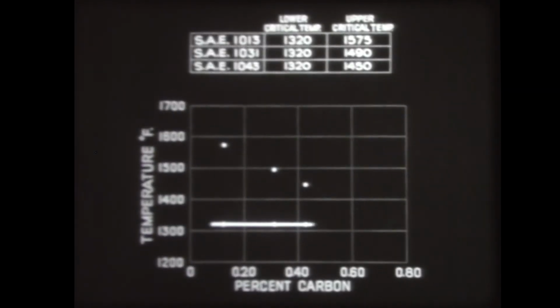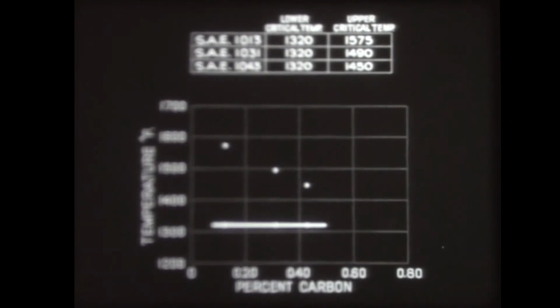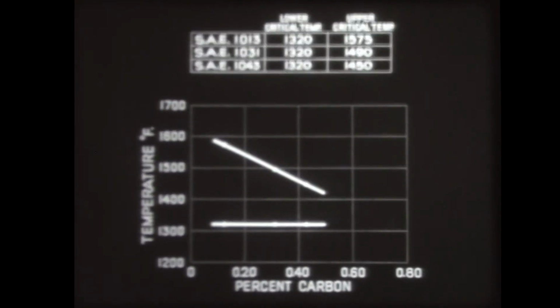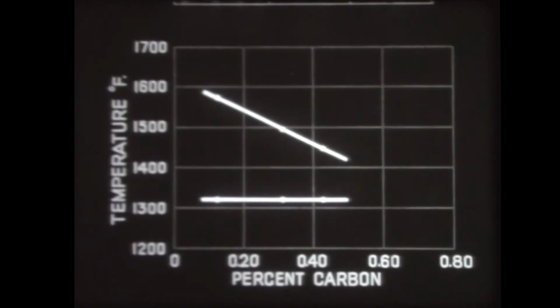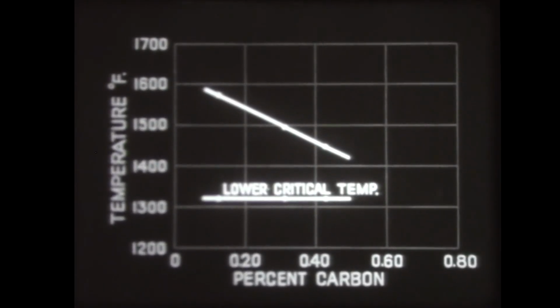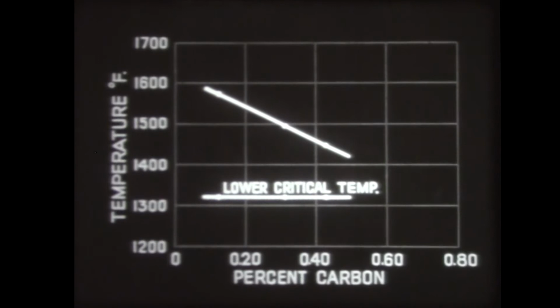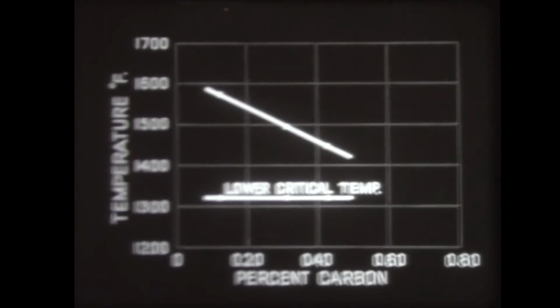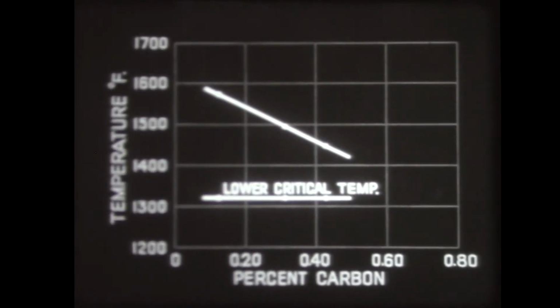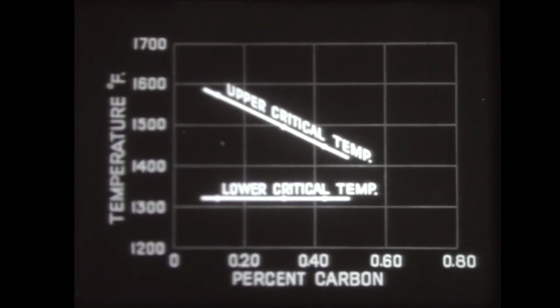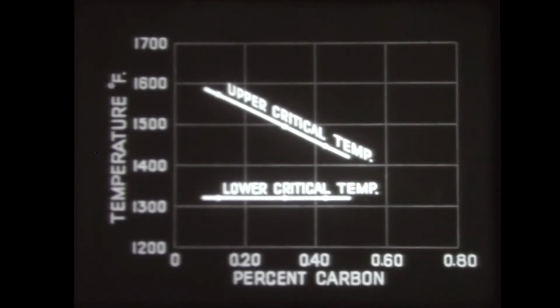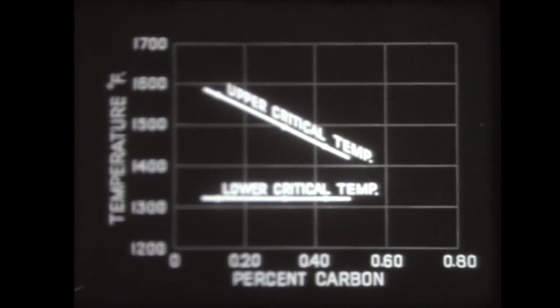Now draw a line through the 3 points of initial hardening and another line through the 3 points of complete hardening. The lower line, the lower critical temperature line, indicates that plain carbon steels begin to harden when quenched from about the same temperature, no matter what their carbon content. On the other hand, the upper line, the upper critical temperature line, shows that the lowest quenching temperature necessary to produce full hardening changes with the carbon content.